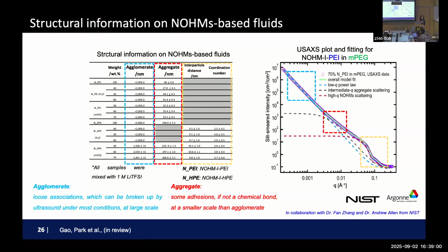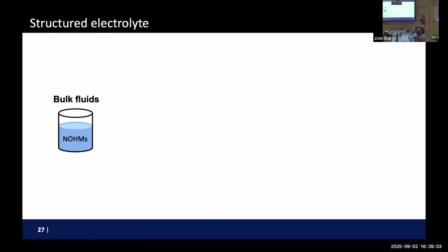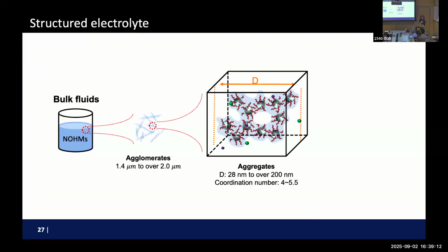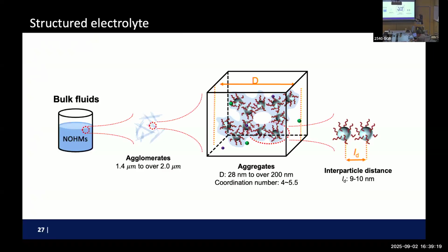So what we realized was, to the naked eye, this material is a very clear solution. Looks very clear. But if you zoom in, there are agglomerates, even micron scale. If you zoom in even further, there are tens to 100 nanometer scale aggregates. And because of that, the interaction between one NOHMs to another NOHMs was very different than what we anticipated. So there was a lot of channeling happening, a very different transport mechanism throughout this fluid with a hierarchical structure. So obviously we can do something.